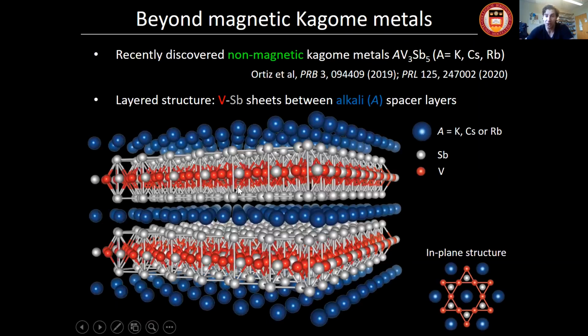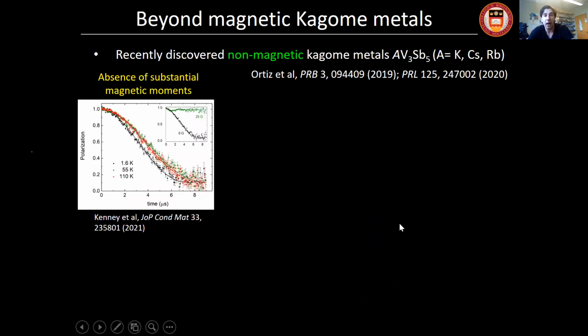They're nicely two-dimensional, where you have vanadium antimony sheets, which is this gray-red slab, stacked between alkali spacer layers. The alkali layer can be potassium, cesium, or rubidium. And in my talk today, I mainly focused on potassium and cesium compounds. And then the vanadium is the red spheres that, if you look from the top view, form this Kagome net. So the Kagome net comes from the vanadium atoms themselves. If you look at what was uncovered soon after the discovery of these systems, well, it was first demonstrated there's no substantial magnetic moment.